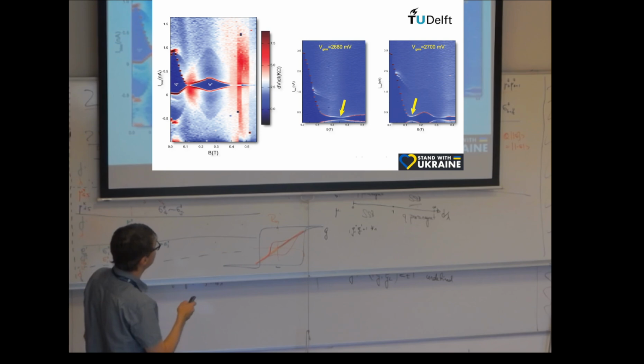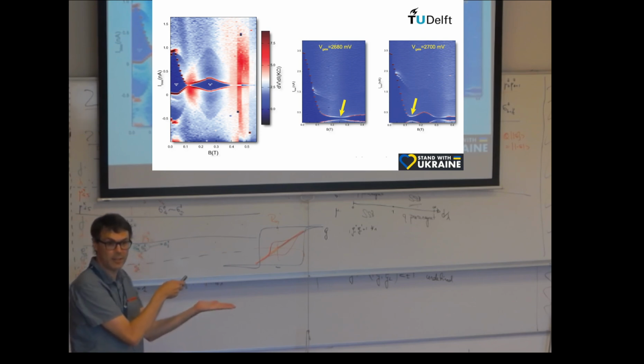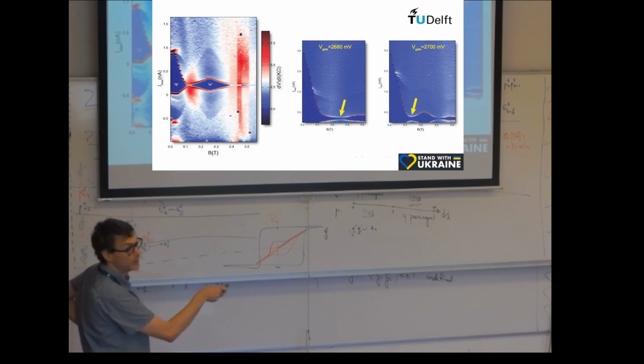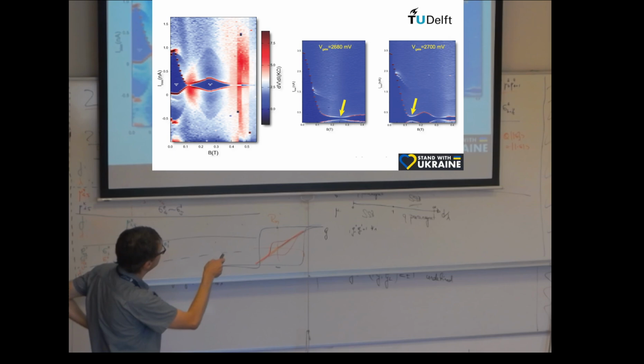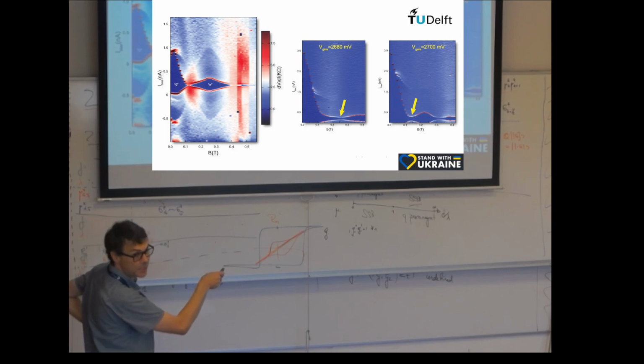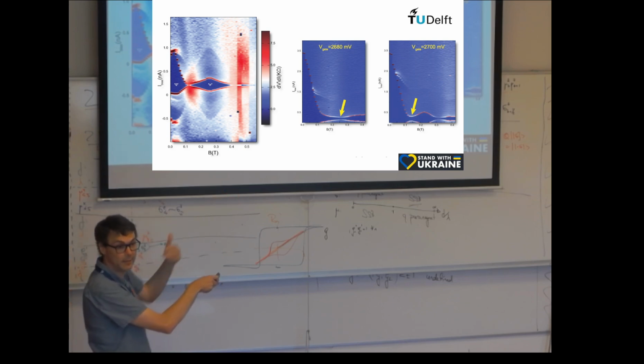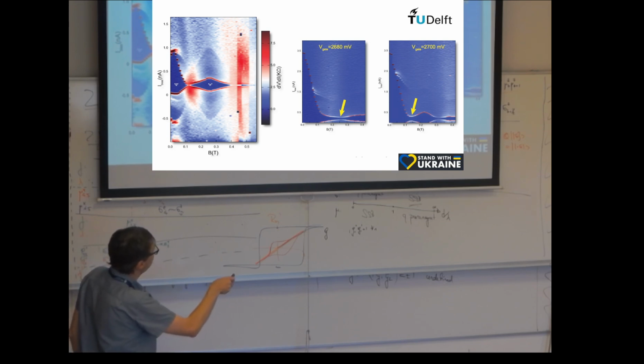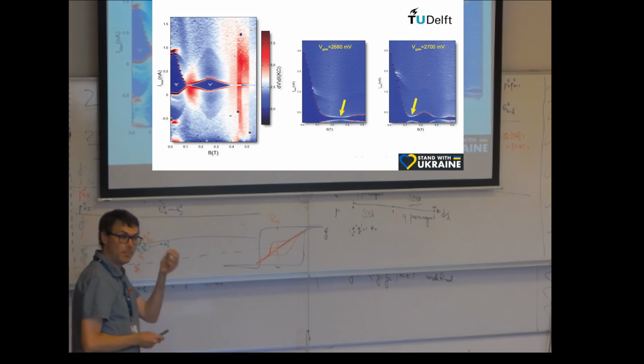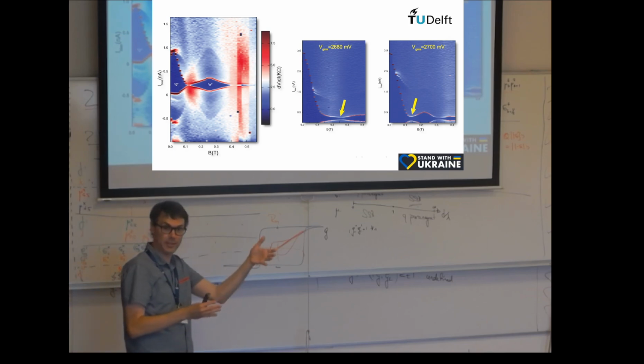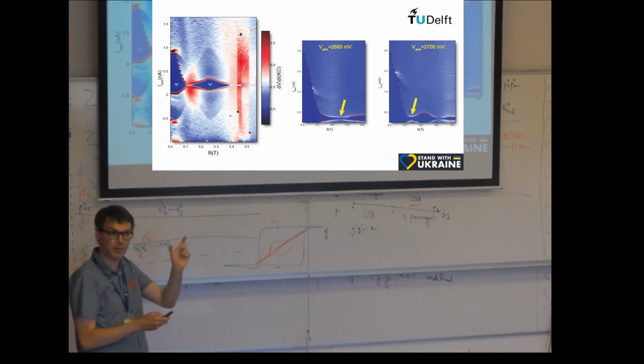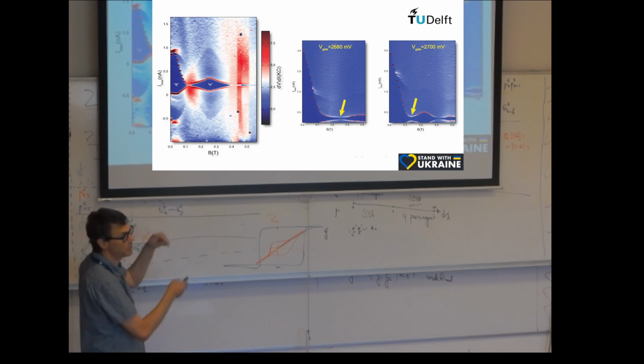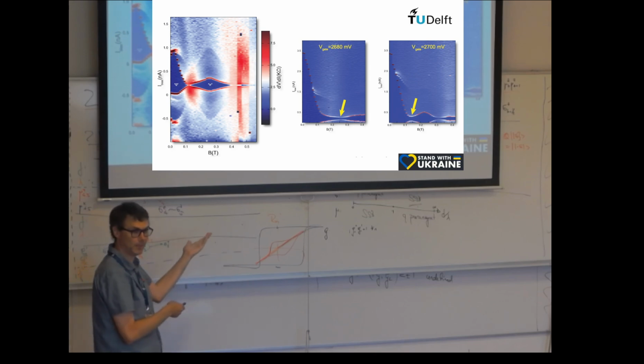What is also interesting is that if I change the voltage on the gate underneath, I can shift this pattern quite dramatically, right? So look, here it decays and goes to something like this. Doesn't actually go all the way to 0, which is interesting. Maybe there are higher order terms like sine 2 phi. This is between 0.2 and 0.3. Here I adjust the gate, goes down between 0.1 and 0.2. So what does that mean? Maybe I'm controlling the Thouless energy, the energy that goes in the equation, right? The pi field is related to Thouless energy. Maybe that's what I'm doing here.